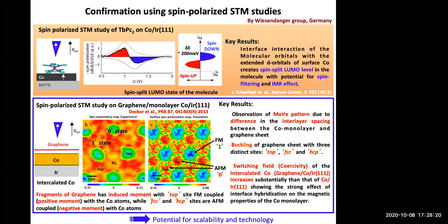So first of all, terbium is in a ligand framework. It's in the ligand field of the molecules. So it's not really a band of terbium, but you can talk in terms of the terbium electronic states. You are essentially looking at the electronic states of the molecule as such by the tip. These states are a combination of terbium electronic levels coupled to the molecular levels, hybridizing together to create molecular states. And it's these molecular states that you're probing with the STM on top.